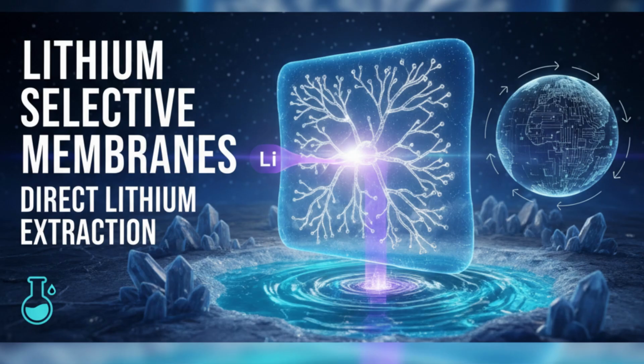And this isn't just lab stuff, right? I read these are actually being tested in real systems. Yes, absolutely. There's work being done using LAGP membranes, for instance, for direct metallic lithium extraction from seawater powered by solar panels. Wow. And they've achieved lithium purity up to 99.9 weight percent using an LLTO membrane in other tests. So the performance potential is definitely there. Okay, so the ISEs are incredibly precise. They hit those mind-blowing selectivity numbers. What's the downside? There has to be a catch.